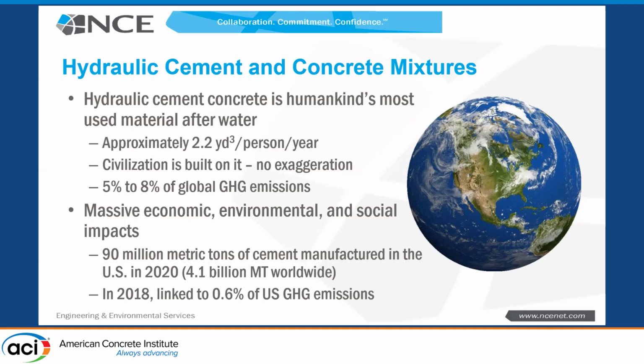Concrete's wonderful. But because it's used so much and it is so robust and so easy to use and forgiving, it's roughly responsible for 5 to 8% of the CO2, the greenhouse gases that we generate in the world. The numbers in the US are smaller as a percent of our economy. We roughly manufacture 90 million metric tons of cement in the US in 2020 versus the 4.1 billion metric tons manufactured worldwide. And that's about 0.6, 0.7% of the US greenhouse gases. So it's a smaller percentage, but that doesn't mean it's not significant and that we are not the focal point of those that want to lower our carbon footprint.